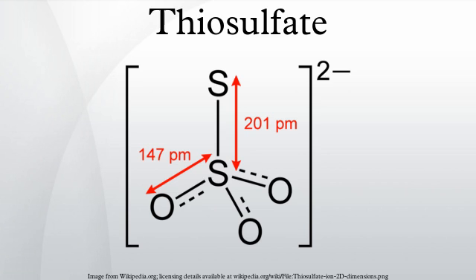Thiosulfate causes rapid corrosion of metals. Steel and stainless steel are particularly sensitive to pitting corrosion induced by thiosulfate. Addition of molybdenum to stainless steel is needed to improve its resistance to pitting. In alkaline aqueous conditions and medium temperature, carbon steel and stainless steel are not attacked, even at high concentration of base, thiosulfate and in presence of fluoride ion.